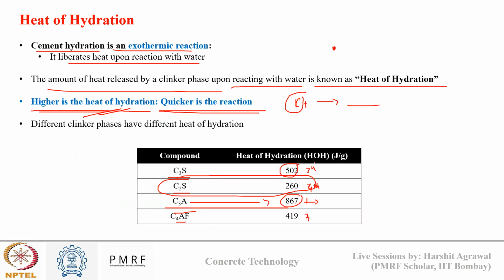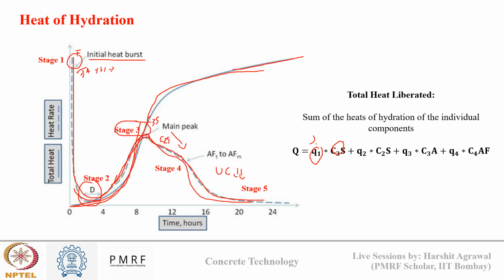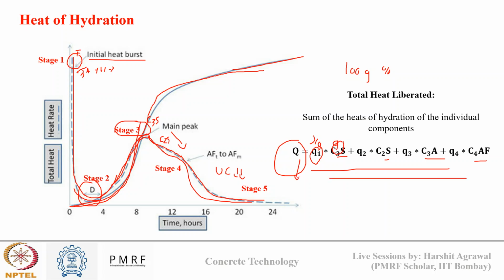This heat of hydration is given to us in terms of joule per gram, and the proportion we will know in terms of gram. So in 100 grams of cement, based on the percentage of each proportion, we can calculate how many grams each phase is. From that we can calculate the total heat of hydration of a cement, assuming that the cement has reacted 100%, that there is 100% hydration.